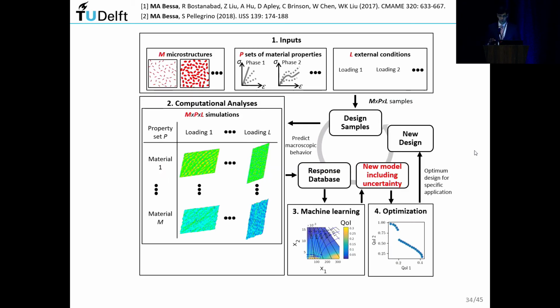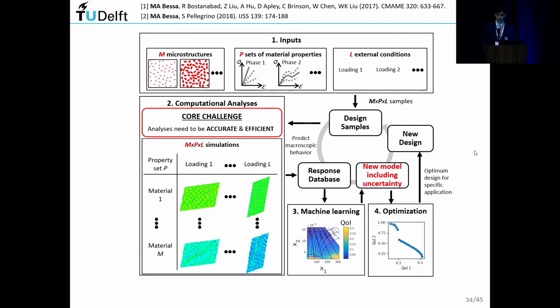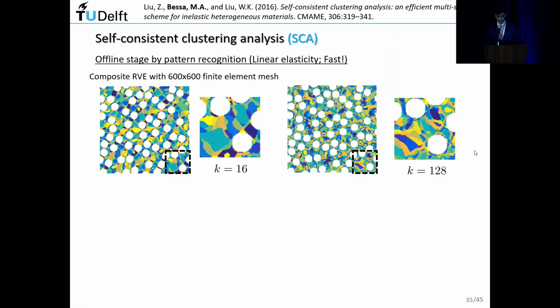Okay, so if we go back to this data-driven framework that we worked on in 2017 and 2018, you define the design of experiments, you do analysis, you build the response database, you have the machine learning, and then you conduct optimization. But you have to make sure that your simulations are fast enough, because if they're not fast enough, like plasticity and fracture simulations, then you don't build a big enough database and you cannot use machine learning afterwards. This is a key issue that the first plenary speaker talked about as well for fluids.